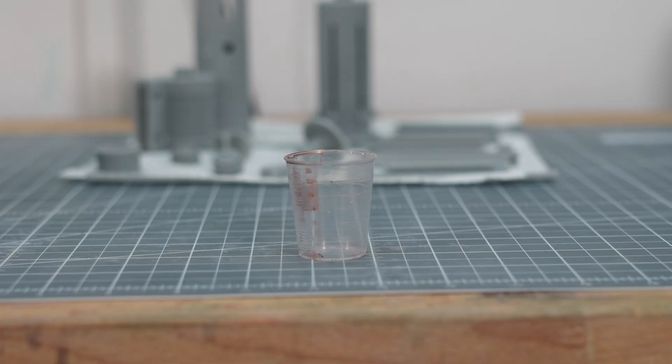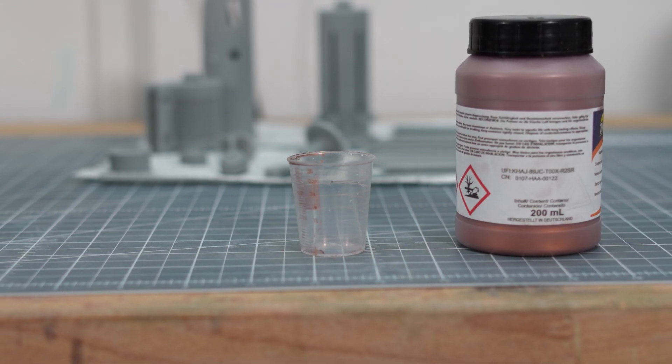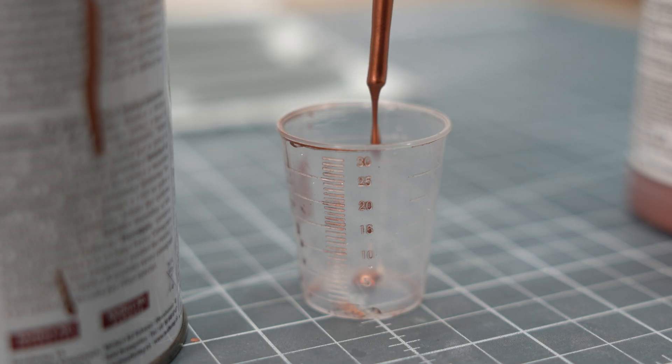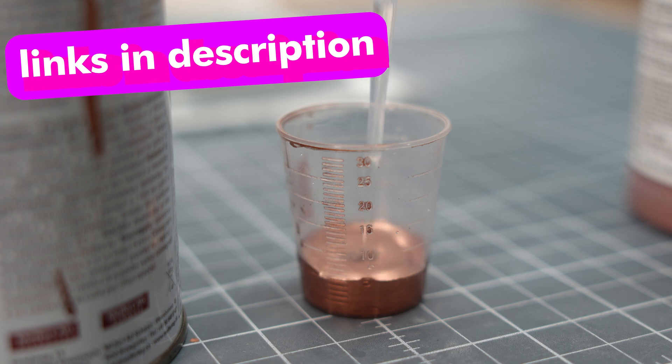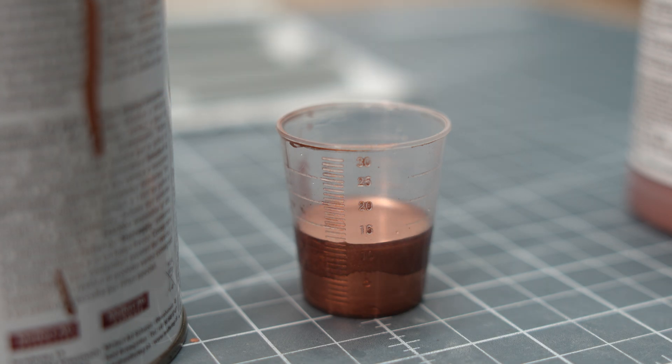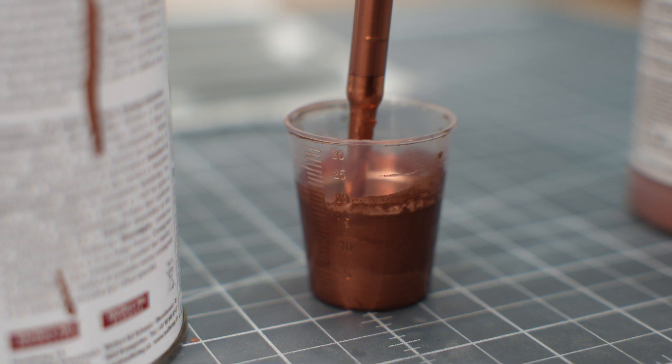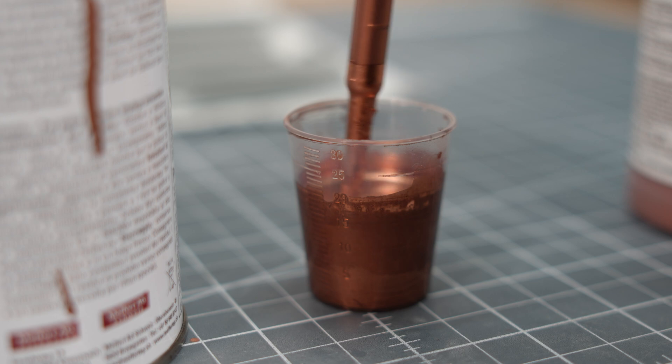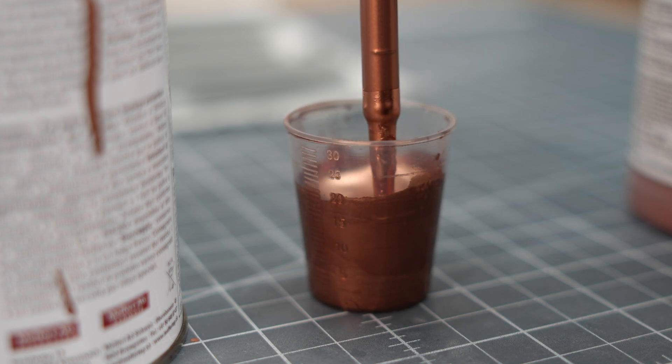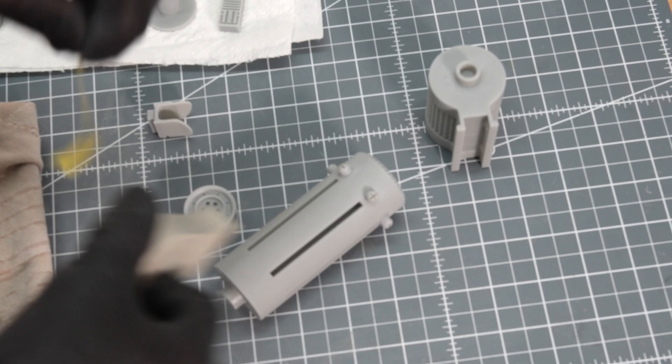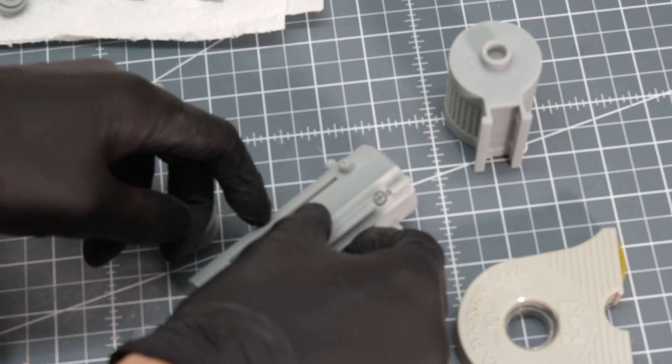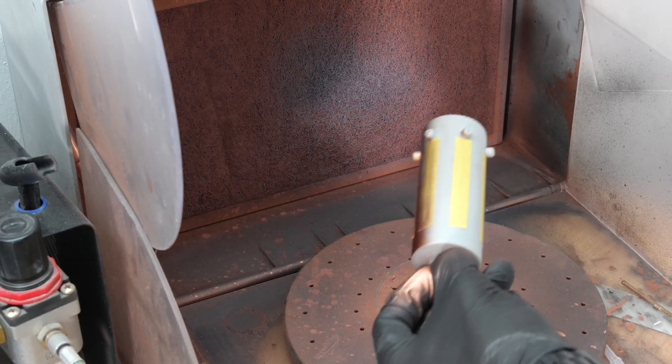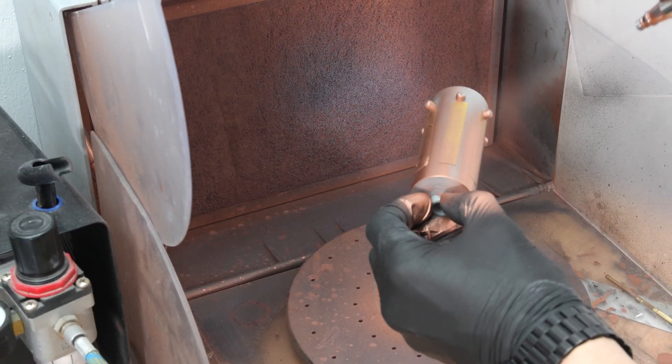The conductive paint I've always used is copper-based and is diluted with a 1 to 2 ratio of acetone. It comes in a durable can. From now on, I will be linking almost all the items in the description, which I didn't do before but was often requested. These are all affiliate links, so if you feel like buying the items, please use these links and I may receive a small commission. By the way, it's a good idea to avoid the clearance issue altogether by masking off certain areas and not electroplating them. Simply use tape to mask them off and remove the tape after spraying.